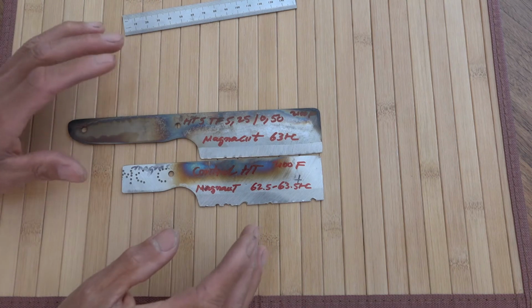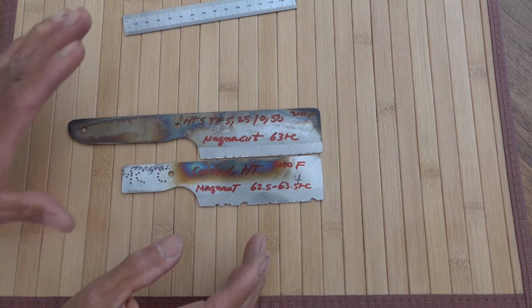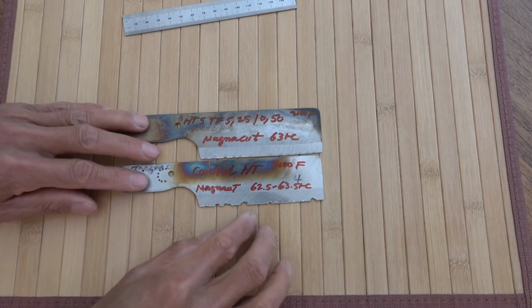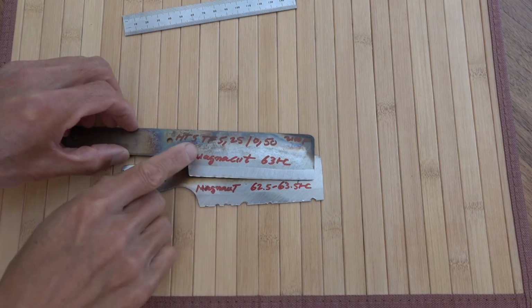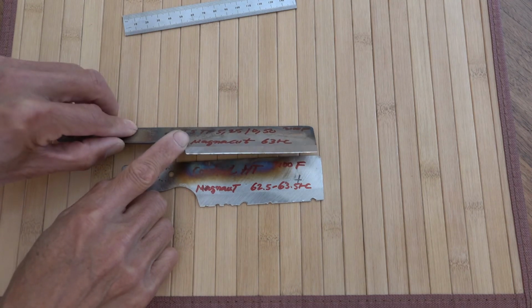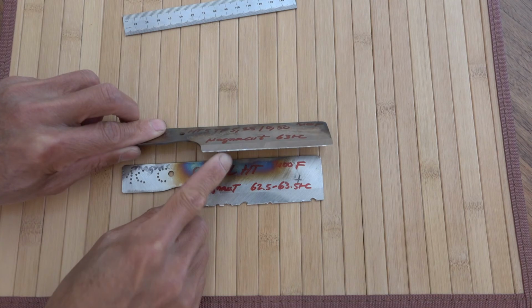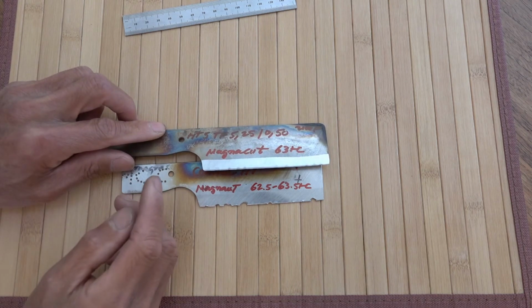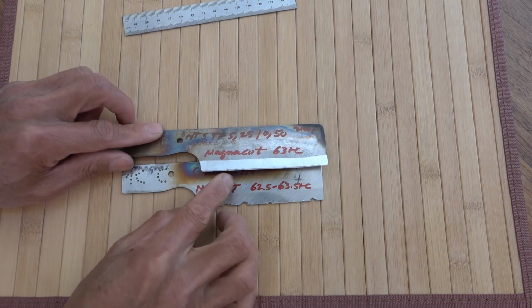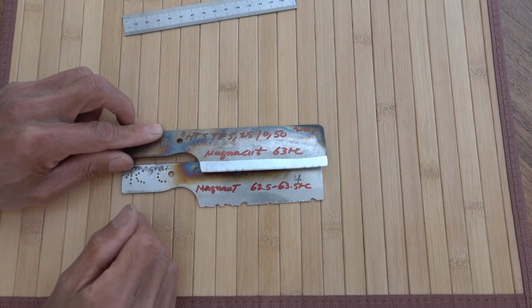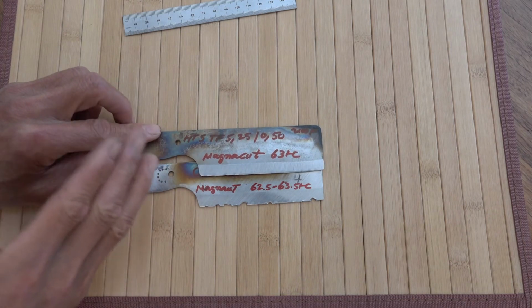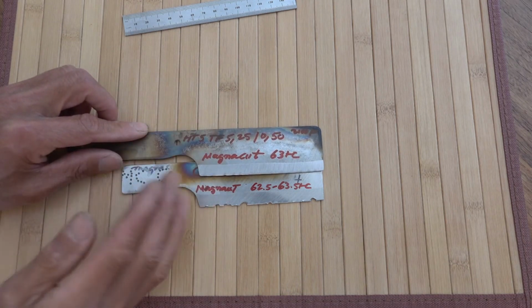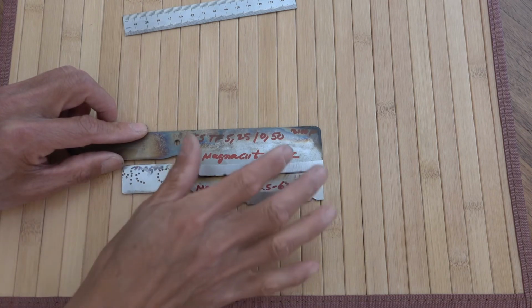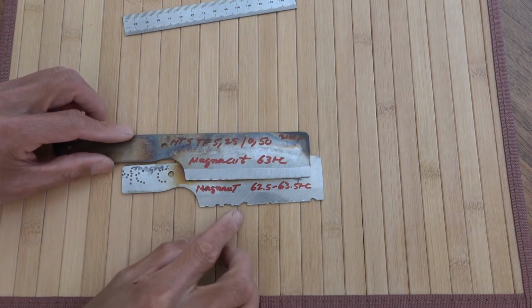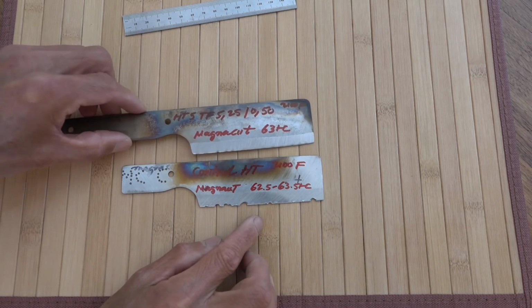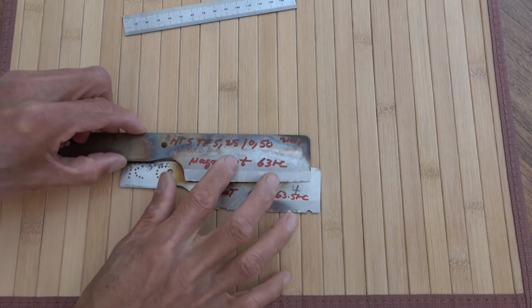All the blades have cryogenic or liquid nitrogen soak. This one did not chip at all; the more serious issue is the edge got deflected. From the previous video of this cutting, you can see that BluntCut MetalWorks heat treated for a lot more impact and shock resistance. This time heat treat, I increased the yield strength and also a little higher hardness. And the outcome, you can see, is Magnacut control versus BluntCut MetalWorks.